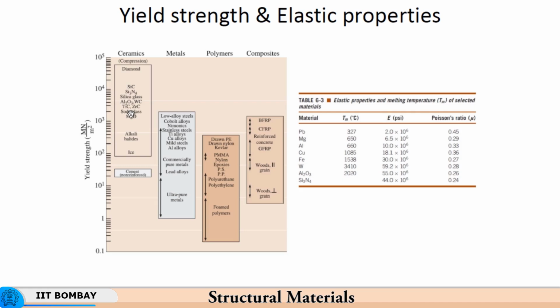As you look at these temperatures, you have different yield strengths and Young moduli. You have yield strengths and elastic properties differing with temperature. Here you see the comparison between elastic properties and yield strength of ceramics, metals, polymers and composites. The yield strength is maximum with diamond ceramics. With composites, the yield strength is very high.